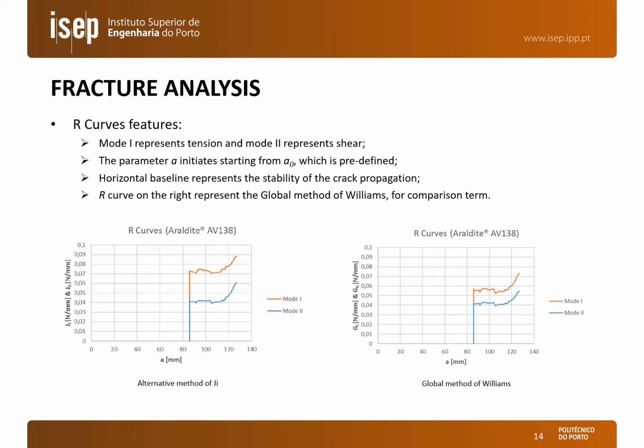Regarding the fracture analysis and beginning with the R curves, here we have an example for one specimen of the tensile and shear R curves. We have here the Ji method and also the Williams method. We can see that the crack length initiates from A0, which is predefined by the specimen manufacturing, and we have a horizontal baseline that tells us that we have a stable crack propagation.